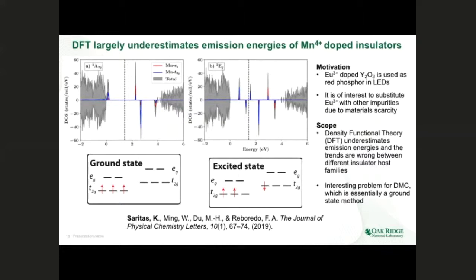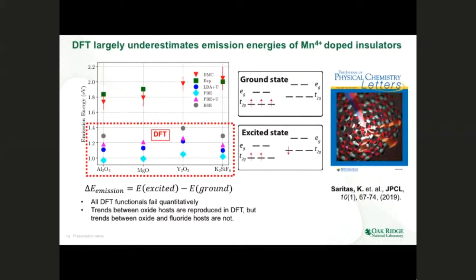And this is the type of electronic excitation that goes on in the manganese atom, and we can see that the excitation is mainly localized on the manganese atom if you look at the eg and t2g levels. So we know that diffusion Monte Carlo is essentially a ground state method, but it is interesting to see how it would perform in a case like this where we simulate excited state behaviors. So far what we did was to choose 4 different host structures, which are aluminum oxide, magnesium oxide, yttrium oxide, and potassium 2 silicon fluoride 6. And these host structures all have manganese doped in them.